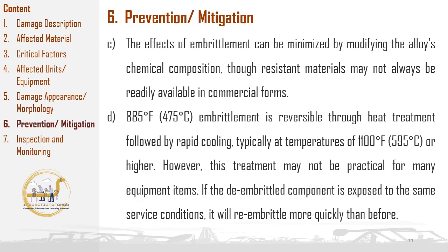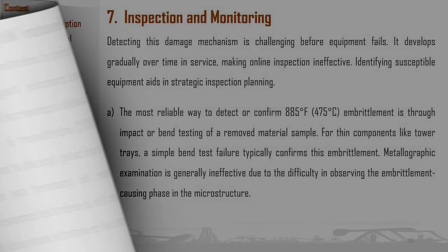However, it's crucial to recognize that this treatment may not be practical for many equipment items due to size, complexity, or operational constraints. Furthermore, if a de-embrittled component is re-exposed to the same service conditions that caused the initial embrittlement, it will tend to re-embrittle more quickly than before, necessitating careful consideration of long-term material management strategies.